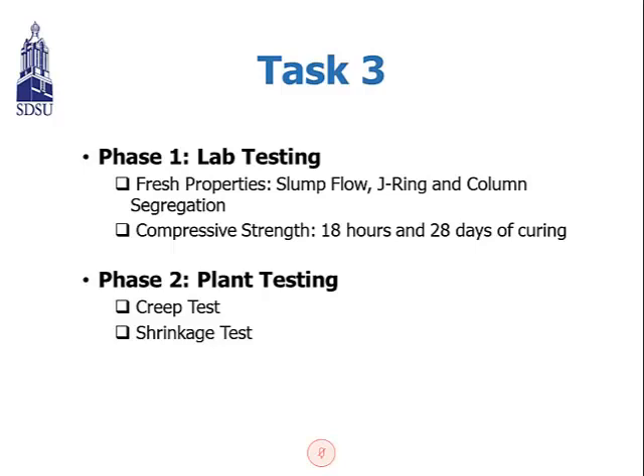Phase 1 lab testing includes fresh property testing: slump flow, J-ring, column segregation, and the compressive strength at 18 hours and 28 days curing. And phase 2 is the plant testing, including the creep test and shrinkage test. It also includes the fresh properties and compressive strength.